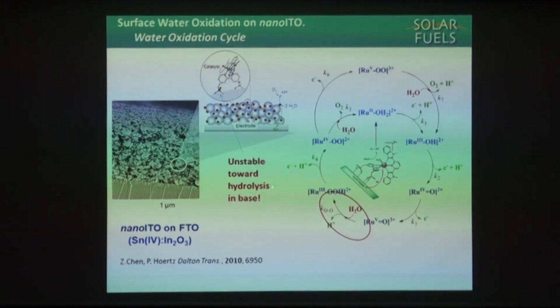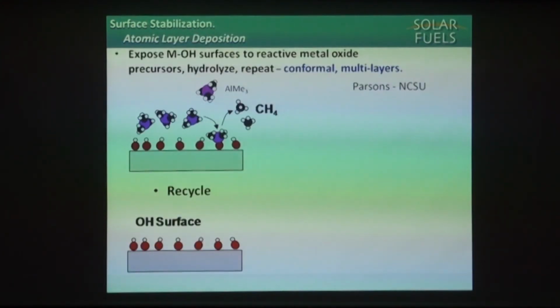But as the pH goes up, what we find is that these nice phosphonate links that are stable in acid are unstable in base. The complex just hydrolyzes off the surface. Kind of standard ester chemistry. To solve this problem, we turn to atomic layer deposition, first in collaboration with Greg Parsons of North Carolina State.